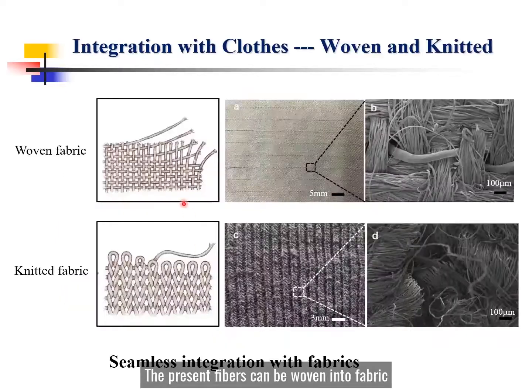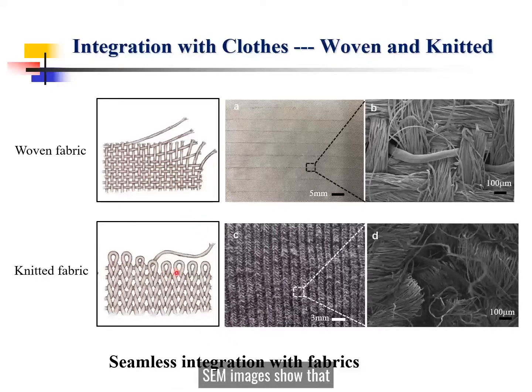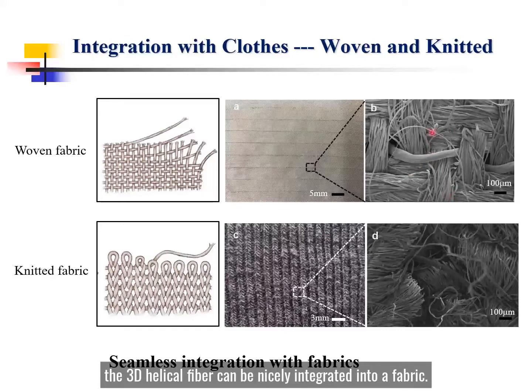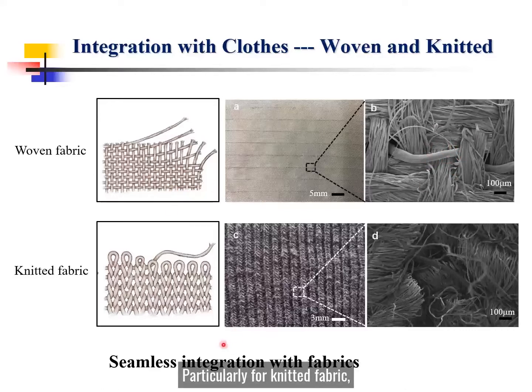The present fiber can be woven into fabric using both weaving and knitting. SEM images show that the 3D helical fiber can be nicely integrated into a fabric, particularly for knitted fabric. The thickness of the fabric is about 1 mm, and the 3D shape of the helical fiber is intact.